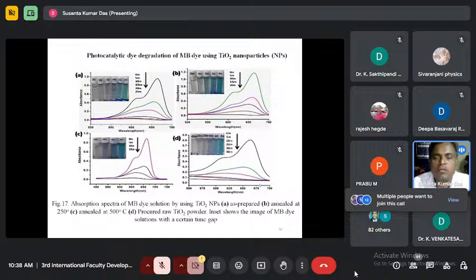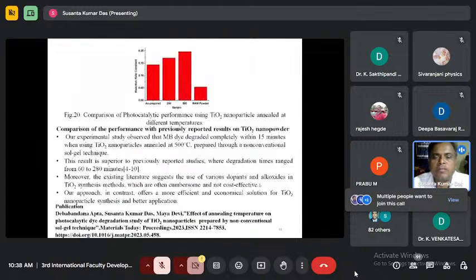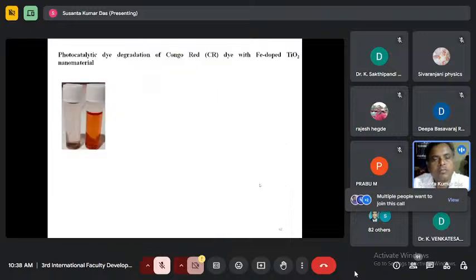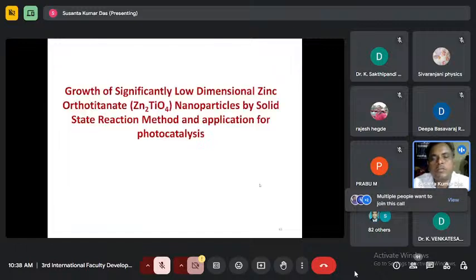And we went for decomposing various materials, and here you can see raw powder. The last one is showing much less, whereas the processed material is showing much higher reaction rate constant. And we had also gone for heat treatment at different temperatures. Then we found different results. This is for optimization, and these are also published. Different types of dye we have decomposed.